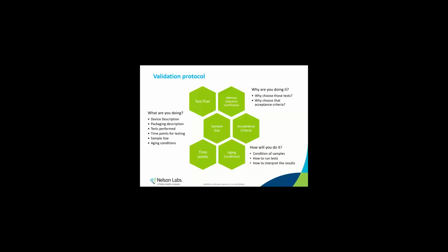The test methods usually don't define what result value is acceptable, so each individual needs to decide what a good minimum value is for their specific product. A good example is the strength acceptance criteria. The minimum seal strength value is what's needed to keep the package closed, and that can vary depending on how heavy your product is or how much stress is being put on the seal, which can be related to product weight and air pressure vacuum changes during sterilization and air transport.